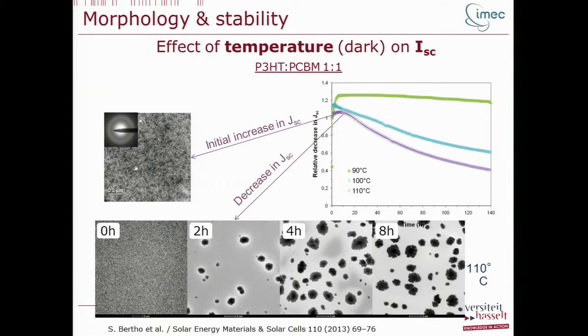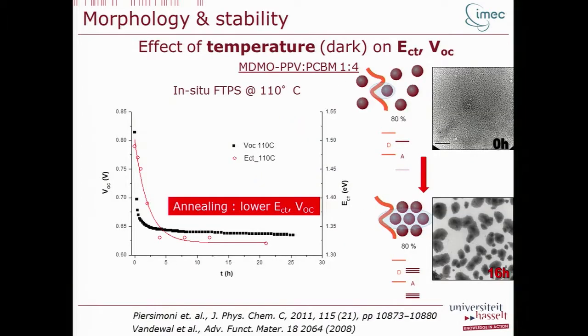But this temperature has not only an effect on morphology and the short circuit current, but also on the VOC and on the charge transfer energy. That's what we illustrate here. VOC goes down if we measure it in situ. Fourier transform photocurrent spectroscopy, the energy of the CT state. Also there we see that a change is occurring.